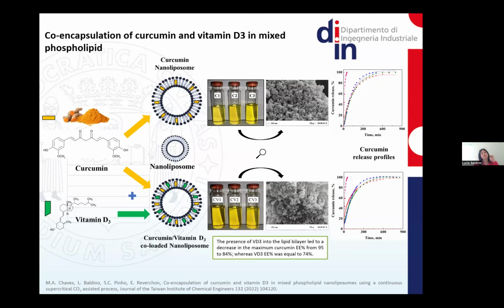As you can see from this graphical abstract, in both cases we obtained nanometric liposomes by scanning electron microscopy analysis. But when we load both bioactive compounds, we detected a slight reduction of curcumin encapsulation efficiency from 95 to 84% due to the presence of vitamin D3, since both are lipophilic compounds. So there was a sort of competition in the same phospholipidic layer. However, in both cases, curcumin release profiles were comparable and diffusion governed the release mechanism.